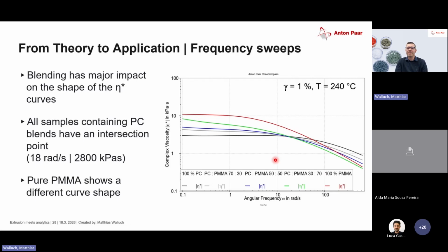Now, what would happen if I did the characterization using MFI? In principle, this would be possible, but a little bit tricky since we have different standards for different materials and different temperatures. So if we want to follow the standards, we are not able to do this at 240 degrees and get the right values out.